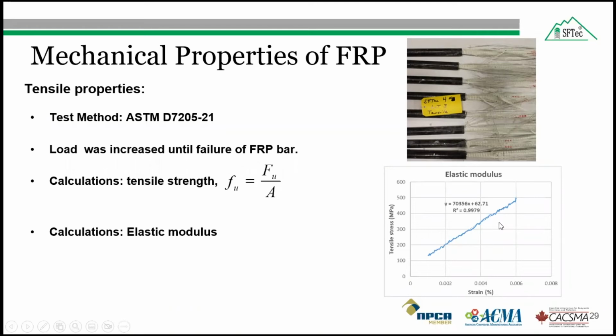And the figure which I am showing is the procedure used in ASTM D7205, not as per CSA S806. In that case, there is a different procedure. So here the tensile modulus of elasticity was calculated by fitting a straight line to the data using the method of linear least square regression analysis, and the strain range selected for fitting the line was within the lower half of the stress strain curve. The starting point of the strain was 0.001, and the end point was 0.006. And these points are according to the latest ASTM D7205/21. Previously, the end point was 0.003, but they have increased it to 0.006 now.